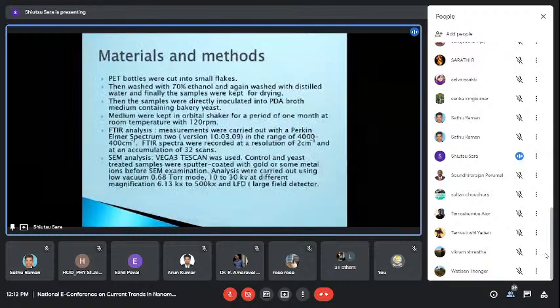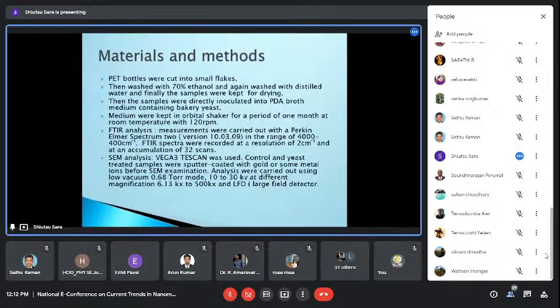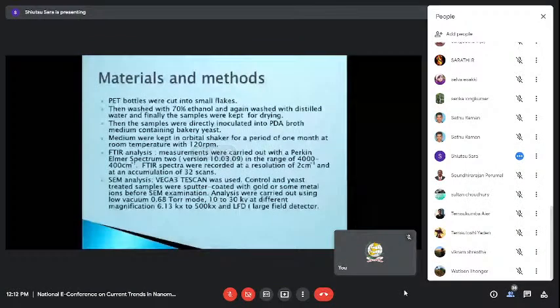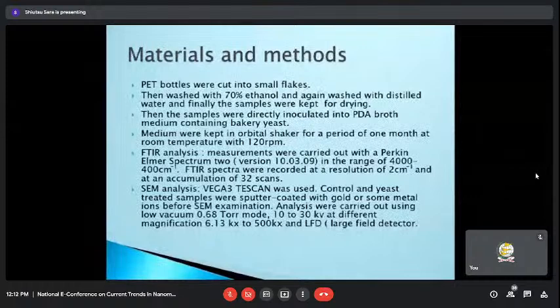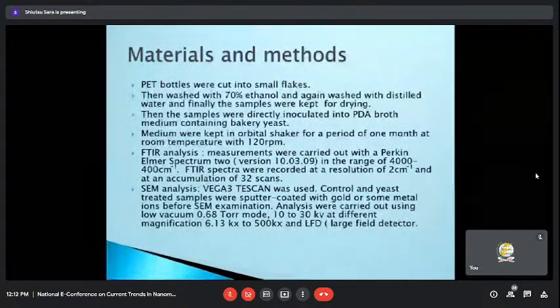So, this slide is about the materials and methods. The important materials which we used were the PET plastic bottles, the PDA broth medium, and also the bakery yeast. The PET plastic bottles are those ordinary drinking bottles which we can easily get from the shop. These plastics were cut into small pieces of about 1 centimeter, and after cutting, they were washed with 70% ethanol. After that, they were washed again with distilled water, and finally the samples were kept for drying.